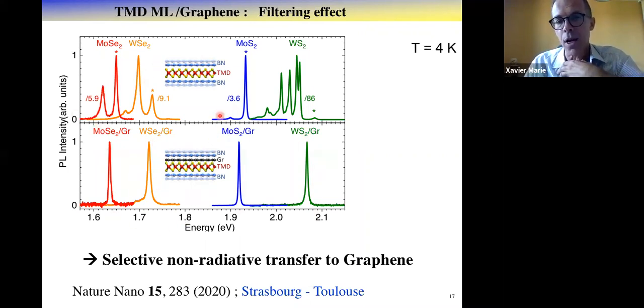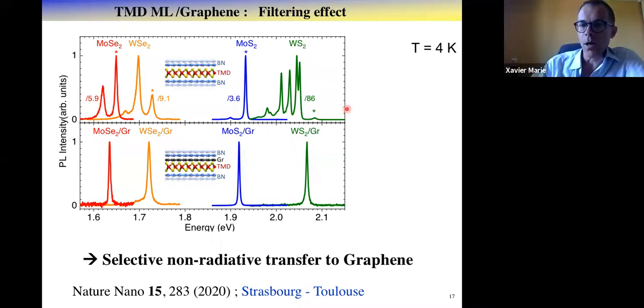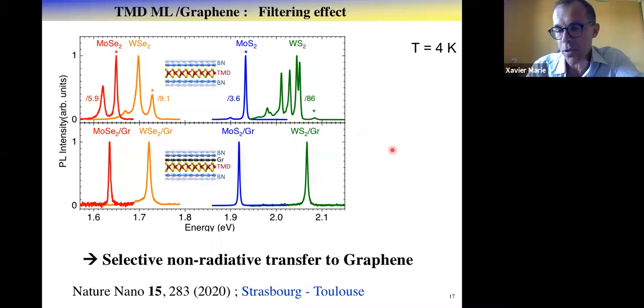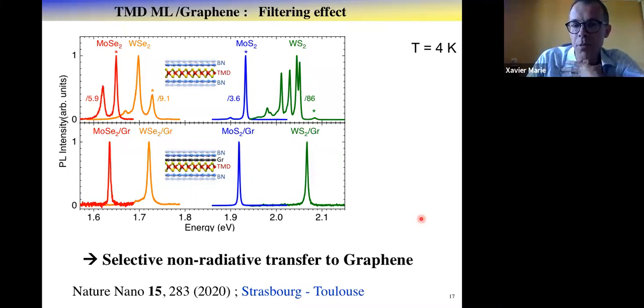In fact, you have filtered all the other emissions, the lower energy lines, which correspond to exciton complexes or possibly transitions involving recombination with localized states or defects, which are usually much longer-lived. And so this low energy transition will be very sensitive to the tunneling of carriers to graphene. So basically they disappear. Whereas you keep your neutral exciton transition, which is a little bit quenched, but not so much at low temperature, because the radiative lifetime of the neutral exciton at low temperature, as I will show in a minute, is very short. It's competitive with the tunneling time, the transfer time to the graphene. So here you have a kind of selective non-radiative transfer to graphene, which can filter your optical spectrum.